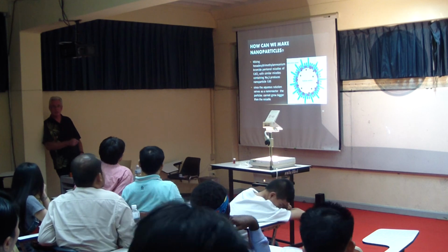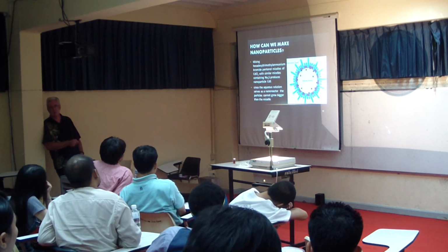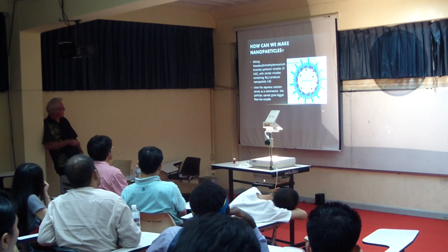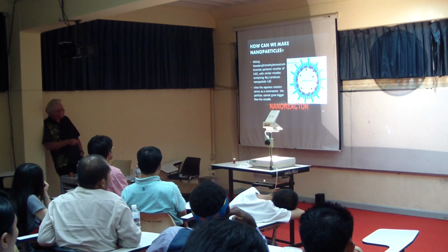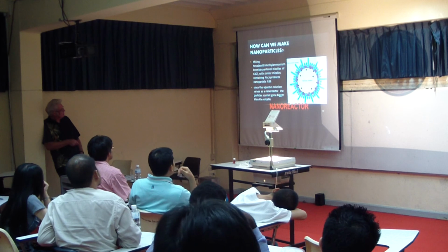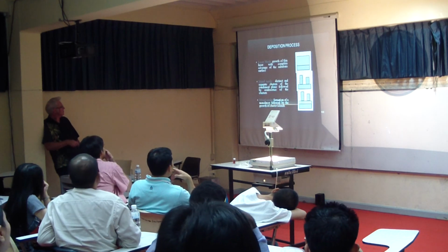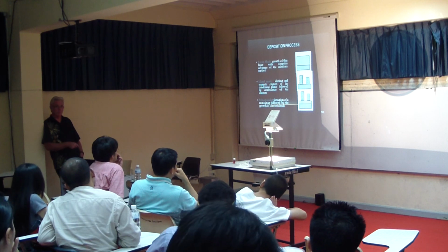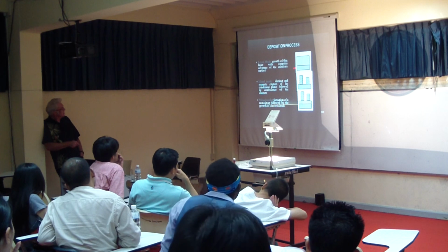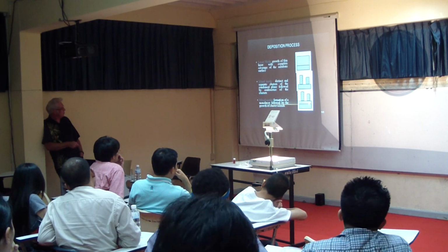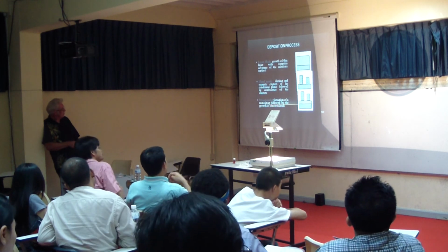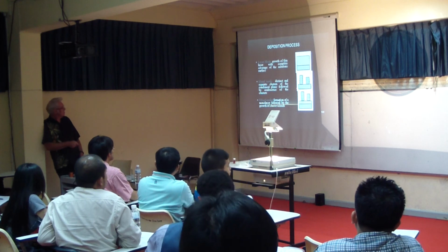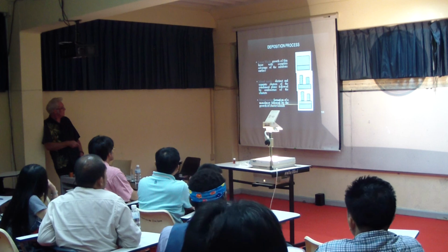So back at UTS, I run a subject nanomaterials. We make zinc sulfide particles. And we change the size of that micelle to give us different size zinc sulfide particles. So we call it a nanoreactor, or I call it a nanoreactor anyway. So we can control that simply by controlling what surfactant I use here. I can use any of the deposition techniques such as chemical vapor deposition or physical vapor deposition. And if I'm clever, I can change things so I can deposit different materials at different times in different places. So I can have a layer mode, an island mode, a mixed mode, and that will depend on my operating conditions. So I can make pillars, I can make films, I can make all sorts of things there.